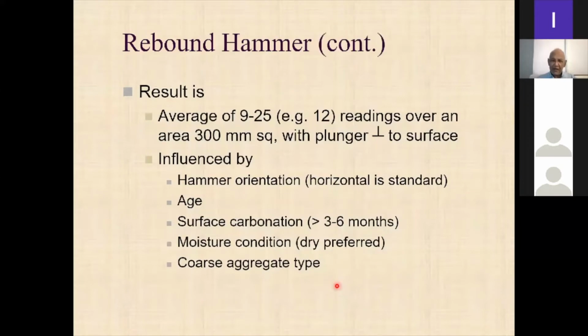Typically, you have to take 9 to 25 readings over an area of 300 millimeters square, that is 300 by 300, right? Typically, people take about 12 readings. Now this result is influenced by the hammer orientation, whether it is horizontal, which is standard, vertically upwards, or vertically downwards. There will also be things like age, surface carbonation, moisture condition, and coarse aggregate type. All of these things will influence the calibration.